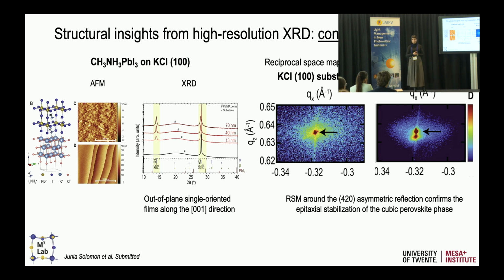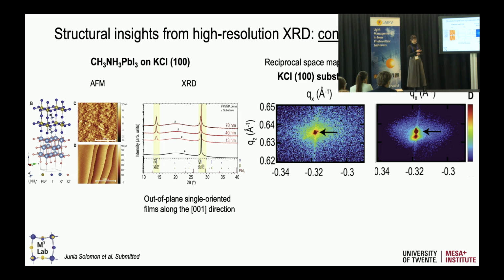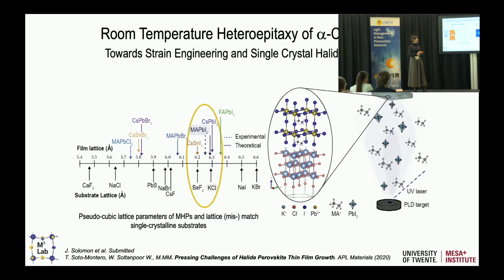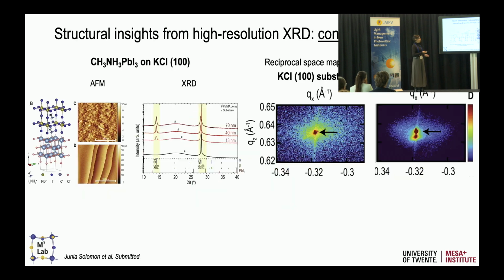Any influence of the substrate temperature while you deposit? Yeah, so that's the problem with MAPI, methylammonium lead iodide: the MA will leave the sample with temperature. But we think the substrate will actually play a role. So we are looking into other substrates as well, but also other deposition parameters, because it can still be optimized a little bit more. You need a little bit more diffusion on the surface to get everything to coalesce. So hopefully we get there. We are trying.